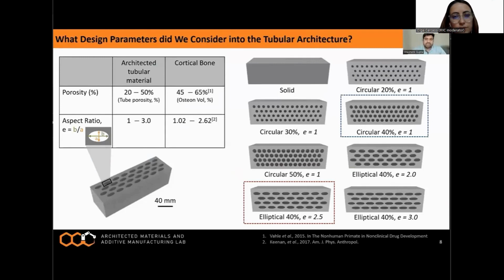Let me expand a bit on design parameters. So we have fabricated tubular architected material with porosity varying from 20 to 50%, and aspect ratio varying from 1 to 3, where 1 denotes the case of circle and any other value denotes the case of elliptical design. These parameters correlate well with the volume percentage and the aspect ratio of the osteons in the cortical bone. Furthermore, I will only highlight the case of circular design with 40% porosity and the elliptical design with 40% porosity and aspect ratio to end this presentation for the sake of brevity.